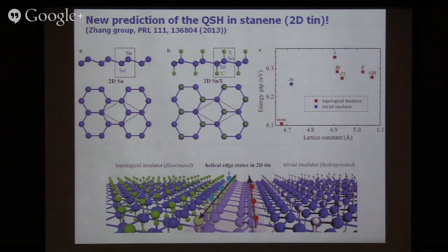But still, both of these materials, the gap is relatively small, about 10 milli-electron volts. So we talk about how we got rid of one extreme condition. Quantum Hall requires high magnetic field and low temperature. But now that we got rid of the external magnetic field, we would like to increase the temperature. But if you have a topological gap of 10 milli-electron volts, it will not work at room temperature.